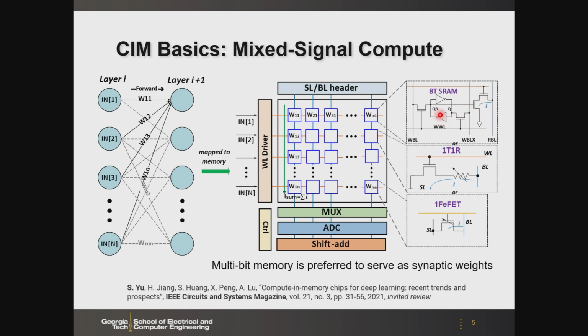And then if you want to have more compact solution, instead of 8 transistor, then you can do 1 transistor, 1 resistor approach, where this resistor could be RRAM or phase change memory, where you can tune the resistance of the memory cell. And then if you look at the most compact solution for this, would be a single transistor solution, where we have the ferroelectric field effect transistor, FeFET. The threshold voltage of the FeFET could be tuned by the polarization of the gate stack. Therefore, we can have different channel conductance to represent the weight. So essentially, we prefer to have multi-level states to serve as a multi-level bit of the weight.